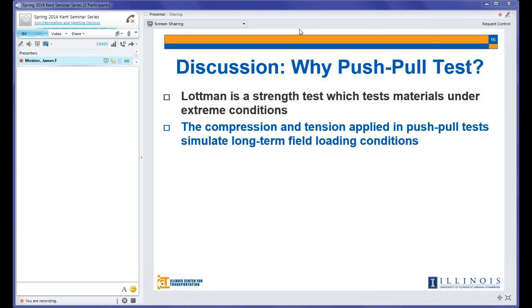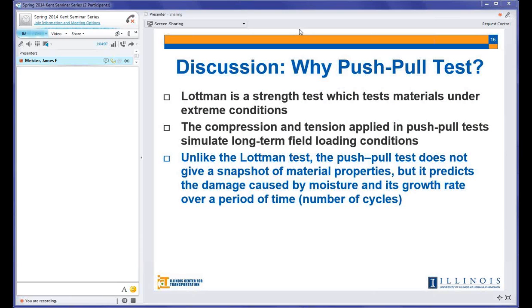One more thing, the Lottman test gives you a snapshot of the material. You only get one value from the Lottman test. That's it, its tensile strength. You will get the TSR, of course, but it's also a reflection of the tensile strength. So you only get one thing out of that test. But from the push-pull test, when you run many samples at different temperatures and different macro strains, you can have a huge map of the fatigue performance and behavior of that mix at any macro strain.